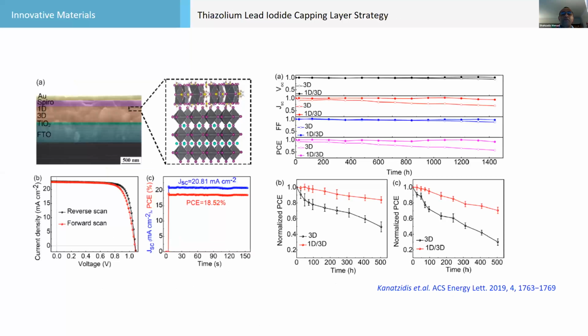This was also, we were working parallelly, and during our submission of the paper, we received feedback from referees that, oh, there's another paper. So it was from Kanatzidis's group on using thiazolium iodide. And they use it as a 1D layer. They call it, after depositing perovskite, they use it as a 1D layer on top, and they reported a very good efficiency enhancement with this thiazolium iodide. And the stability enhancement is very good, and they are much more stable here.